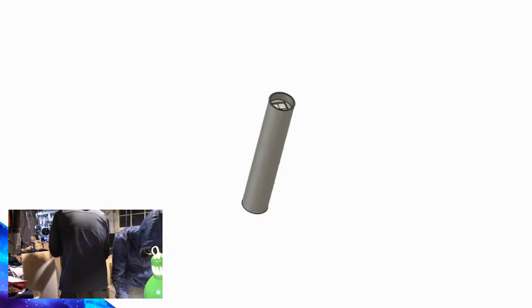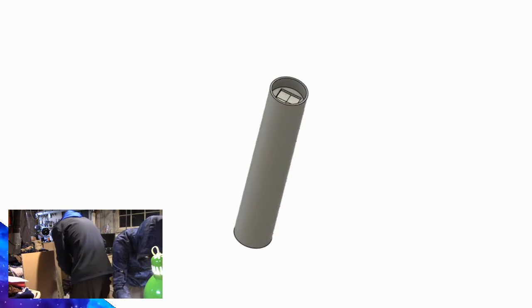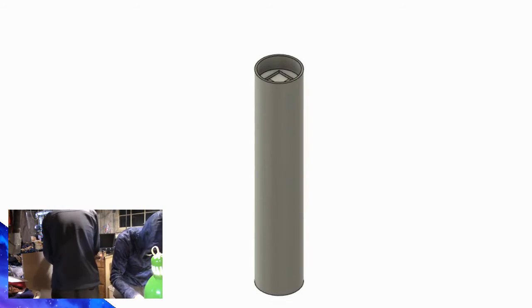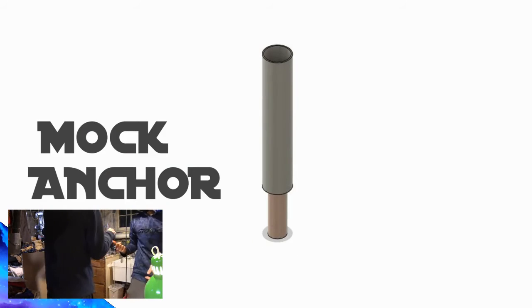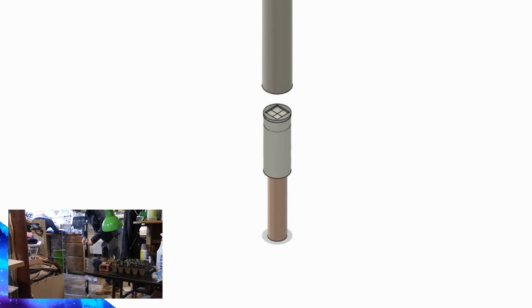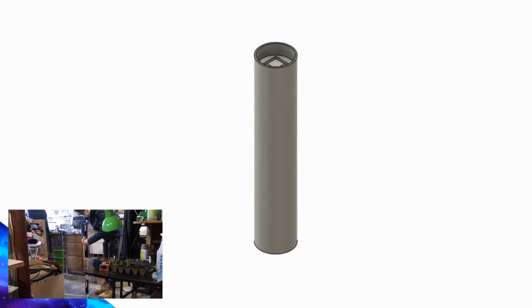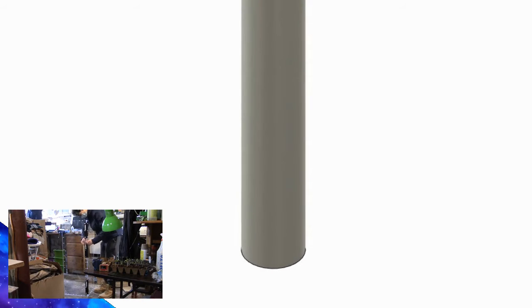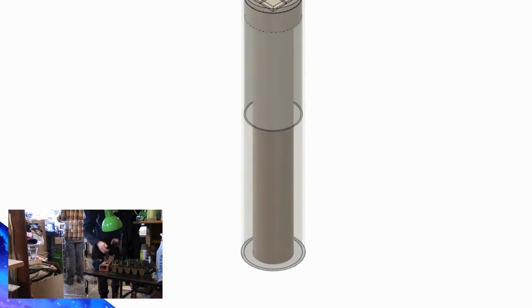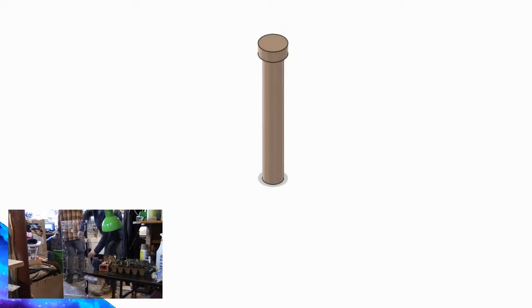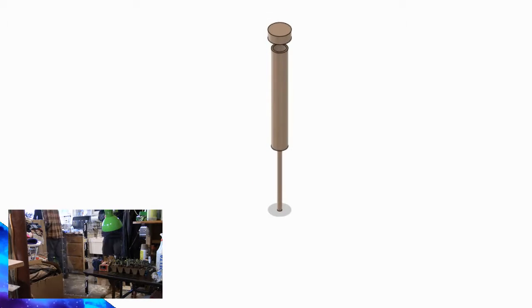To test the concept of using a heat sink inside a helical anchor to cool thermoelectric plates, we designed a mock anchor, a proof of concept model that could be tested in the test rig. The helical anchor was mocked by a steel pipe. For our test, the absence of the helical plates did not affect the performance of the radiator cylinders.